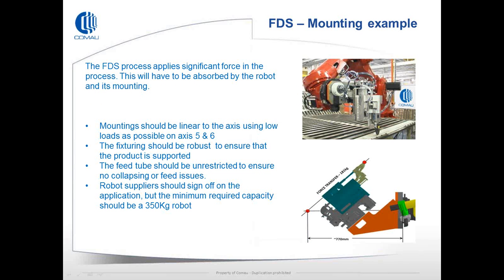This is just showing a typical mounting example where we've got the spindle. This is mounted onto a robot. Okay. During the actual process, a significant amount of force is applied, and this has to be absorbed by the robot and its mounting. So the mounting should be linear to the axis for low loads on 5 and 6. The feed tube should be unrestricted to ensure no collapsing or feed issues. And the robot supplier should always sign off the application, but normally a minimum capacity carrying robot of approximately 350 kilograms is required.